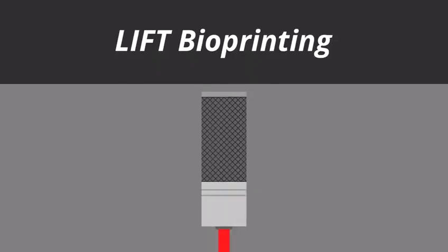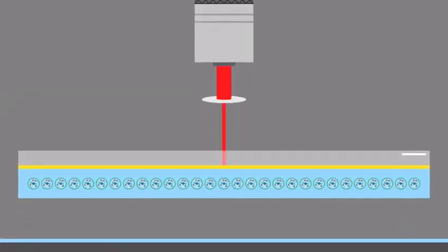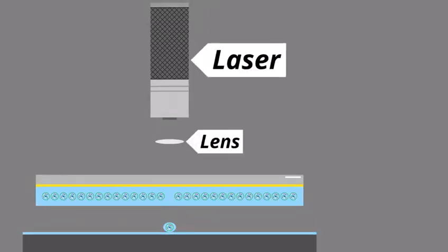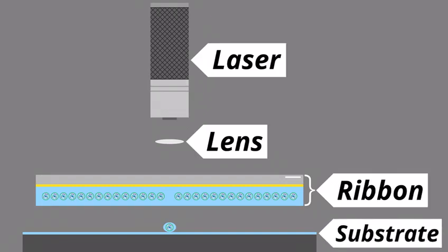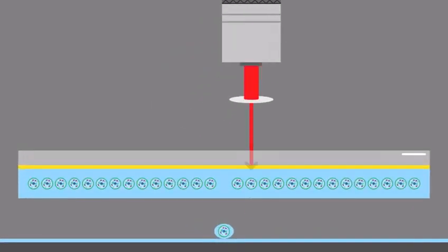Laser-induced forward transfer bioprinting uses lasers to accurately position cells on a substrate, or the place where the tissue will lie. Laser-induced forward transfer bioprinting consists of a laser, a focus lens, a ribbon, and a substrate. The ribbon could contain a sheet of transparent quartz glass with a very thin gold coating and a coating of bioink. When the laser reaches the gold, it heats it and greatly expands it, propelling a very small amount of bioink to the substrate, which will have been coated with hydrogel to dampen the kinetic energy of the droplet of bioink. This laser is quite precise, and hence this method is also quite precise.